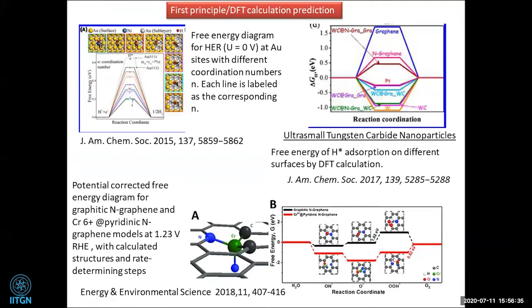These are a few examples; I just took three DFT first principle calculation papers on nanoparticles for the hydrogen evolution reaction. The first one, on the left, is on gold nickel alloy nanoparticle. This is related to what I discussed, that being a nanoparticle, how it is effective and how useful it is. That's what I wanted to show. In this gold nickel alloy, when they did the reaction, there used to be leaching of nickel.